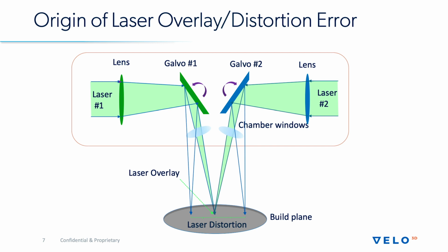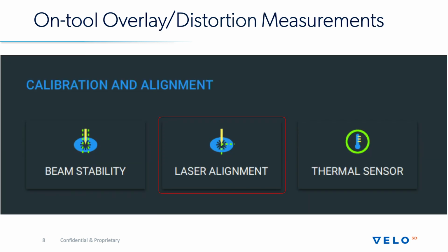There's always some error associated with this, though, and we would call that error the laser overlay error, which is basically how far the two beams are away from each other when nominally targeting the same spot. The second form of error that happens at this point is laser distortion, which is when you take a specific beam and you move it a pre-described position along the build plane. How far does the laser beam actually move when you move it along the build plane? So if I'm targeting 100 millimeter travel, do I actually get 100 or do I get 99 or 101? These are the two common sources of geometric errors when building parts on multi-laser systems.